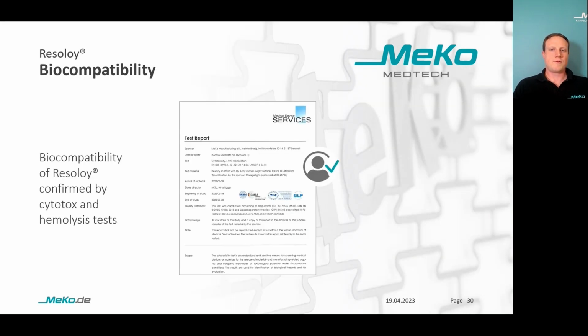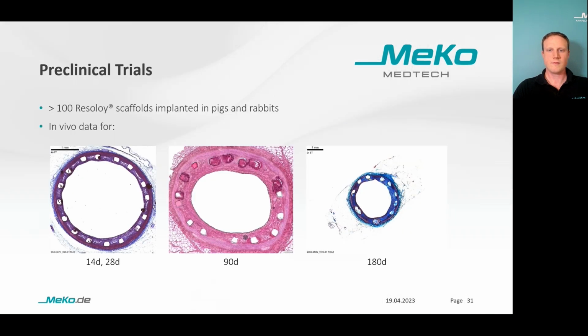Biocompatibility of Resoloy was proven during several biocompatibility tests like hemolysis and cytotox tests according to the ISO 10993. And maybe most important so far, MeKo and partners of MeKo tested already more than 100 scaffolds of Resoloy in the coronaries of pigs. And MeKo can supply customers with in vivo data for several time points like 14, 28, and 90 days.